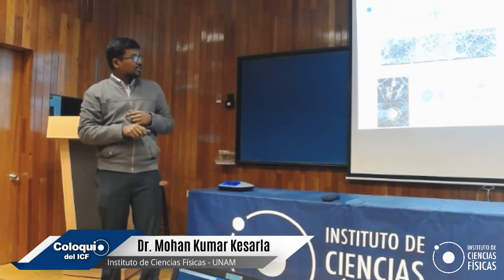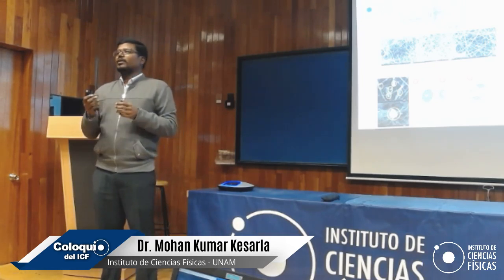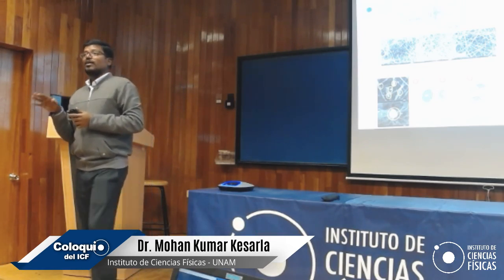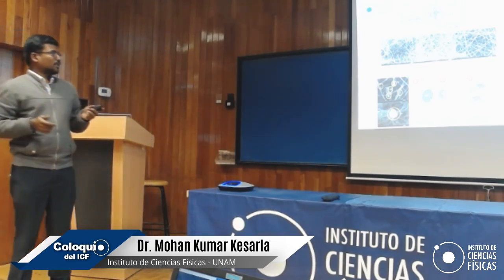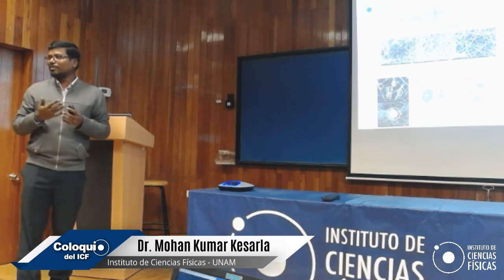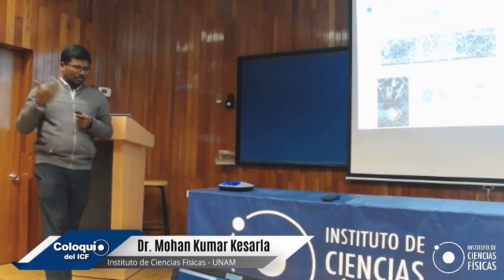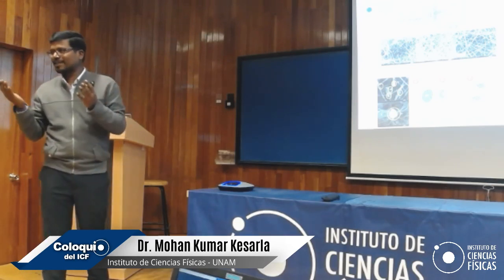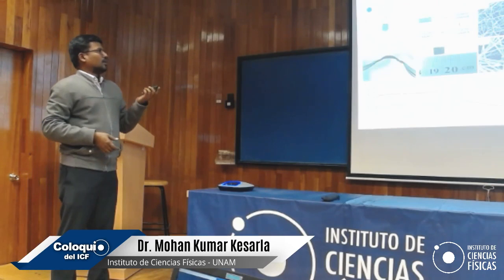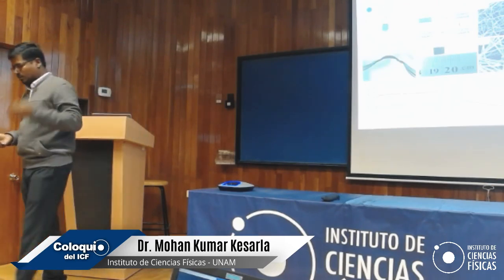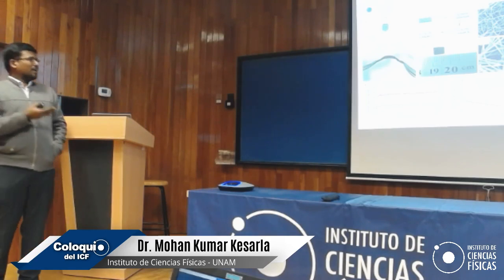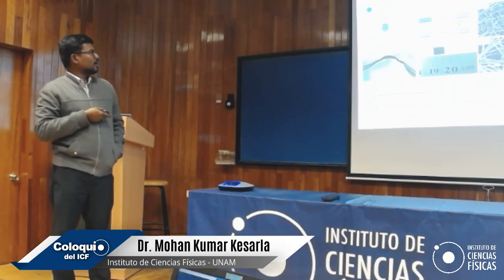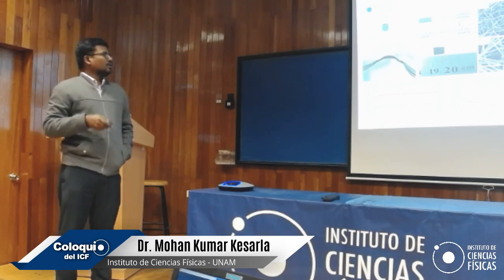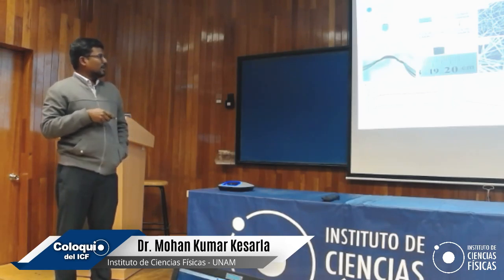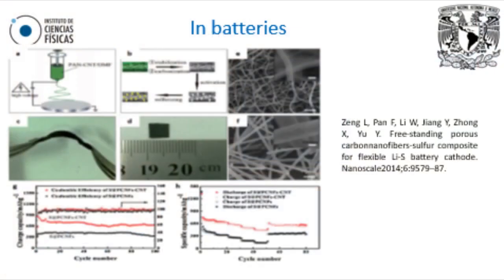And here once again we tested up to 200 milligrams of nanofibers. For sure we are going to get 100% chromium reduction. That's the beauty with these nanofibers. We also tested the colorimetric method with the National Laboratory of Mexico for exact concentrations, and it matches exactly the colorimetric test and what we proved. Apart from this, fibers are also used in battery technology. They incorporated carbon nanotubes into polyacrylonitrile and use it in the lithium-ion battery, and they get good charging, discharging, and cycling capacities. So this is one more important application.